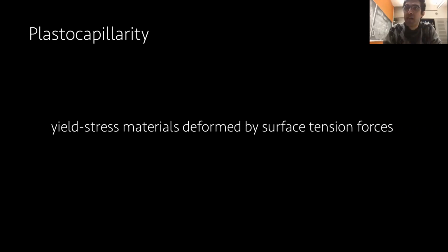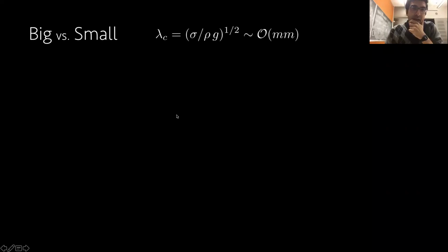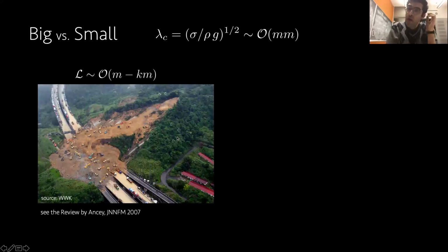To see when plastocapillarity is actually important, we should look at the scale of the problem. Obviously a free surface must be involved, but at what size, that's the question. The easy way to do so is to look at the so-called capillary length scale. This is what I'm showing here with lambda c, which is the square root of the surface tension coefficient over the multiplication of density times gravity. So these are material properties. If you look at water, for instance, this is always of order millimeter, right? But if you look at the literature on free surface viscoplastic or yield stress materials, the majority are looking at scales that are much larger.